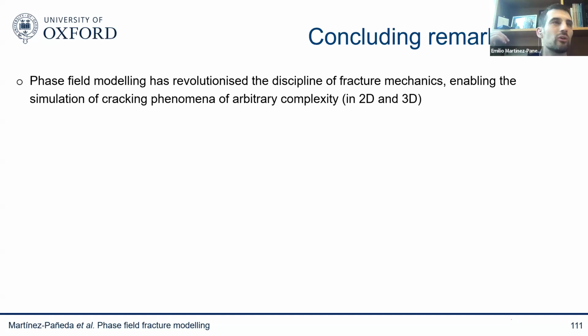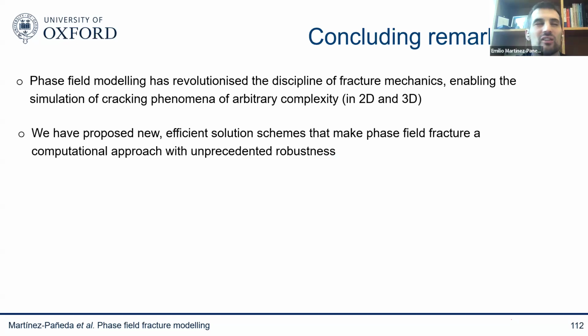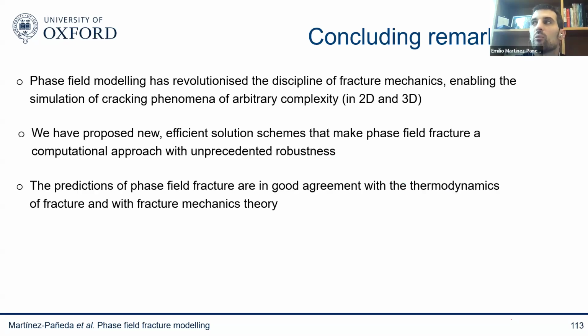We have shown that you can capture any arbitrary complex problem, 2D, 3D, no matter if you have crack branching, crack coalescence. We have tried to contribute to this community by providing new solution schemes that I believe can make significant progress in capturing cracking processes efficiently and robustly. We've also shown that phase field methods are not only computationally robust, but they also deliver a very good agreement with experiments, with conventional fracture mechanics theory. So it's a method that is physically sound.